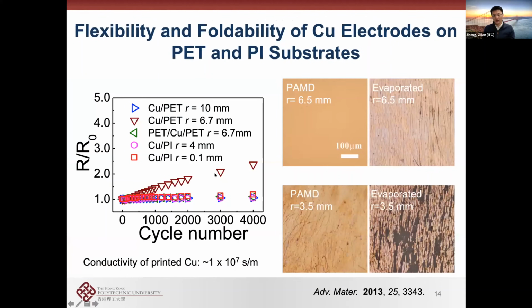So how does the conductivity, or the resistance, look? The conductivity we measured for the thin film is about one of the very best ever reported through an electroless deposition process, 10⁷ Siemens per meter. But the key thing is that when you bend the material on top of flexible substrates, they don't get destroyed. So this PAMD is the one grown by our method.